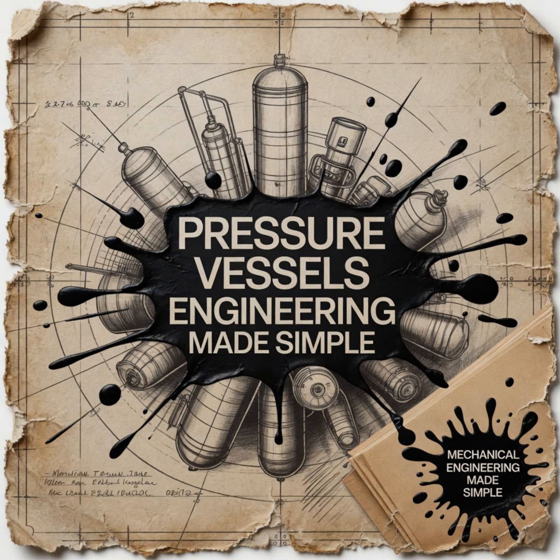What kind of destructive testing? They give you the precise yield strength, the ultimate tensile strength, the elongation percentage, and often the impact toughness at specific low temperatures. I imagine the carbon content is a huge factor there. Oh, massive. Because if a mill accidentally sends a plate with a slightly higher carbon equivalent than specified, it might still look like the right steel, but once the welders hit it with an arc, the chemistry takes over. Exactly. Higher carbon makes steel harder and stronger, but it also makes it vastly more susceptible to cracking when rapidly cooled. Which is exactly what happens during welding.